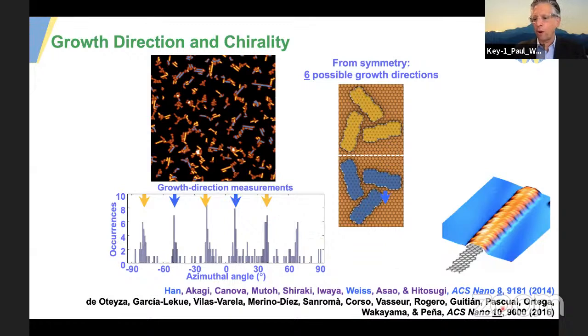Nacho Pascual, a former postdoc in the group, now working at Nanogune in San Sebastian, took the next step, which was to take a vicinal surface in which all the terraces are in the same direction. In that case, by using those narrow terraces, he only got a single chirality of the graphene nanoribbons everywhere on the surface. So I thought that was really beautiful data that we're now following up with measuring spin properties of these nanoribbons.